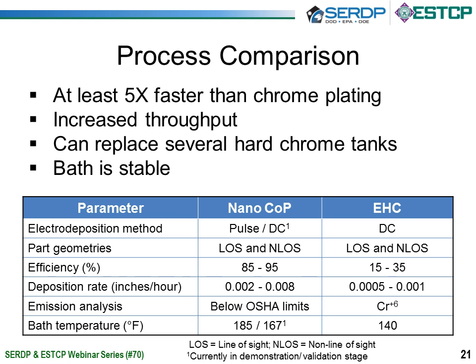The other advantage is since you're not producing a lot of hydrogen at the cathode, you have significantly less gassing that comes off the process and a lot lower mists. Through the emission analysis that we've looked at, it's been well below the OSHA limits for cobalt. And the bath temperature is a little bit higher than that of chrome, which we're addressing also in this current project, which I'll talk about a little later.